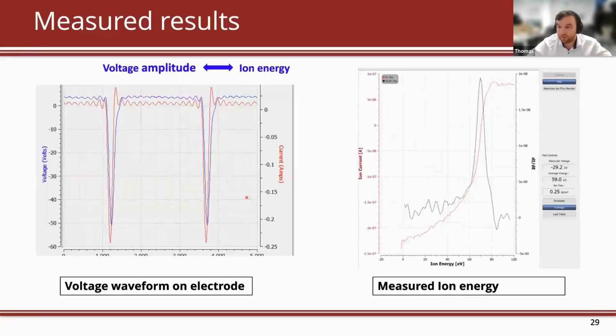If you look at this data that we collected last time, when we had the transformation, the voltage we're getting on the sensor was minus 50 volts, and the ion energy we're getting is 70 volts. On this chamber, the plasma potential is 20. So you can actually get a direct measurement of what the ion energy is, as long as you know the plasma potential. But the plasma potential, as you've seen earlier, does not shift too much. It only shifts a few eV as you change the top power. So it's that easy to do, and with our sensors, you can get live feedback on what's happening as you change these parameters.